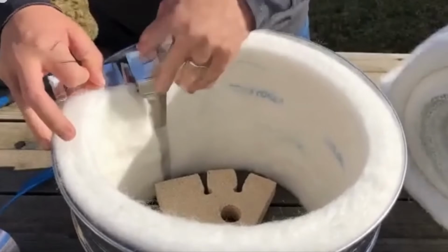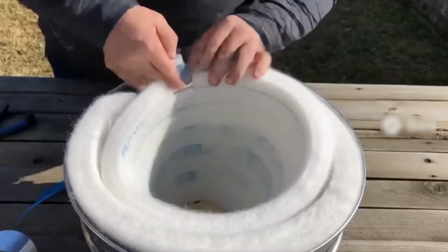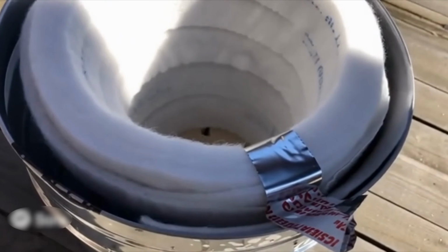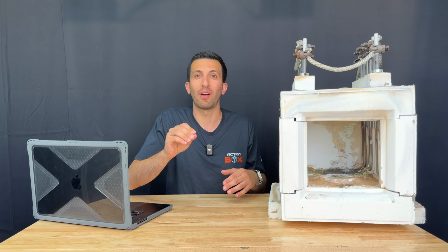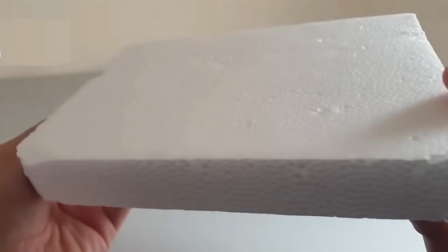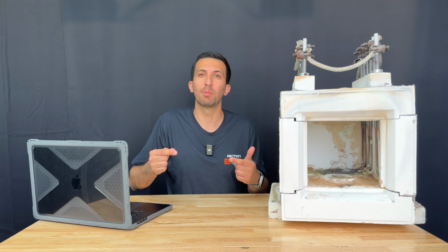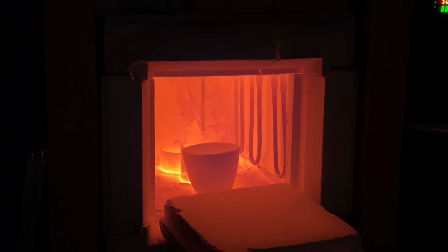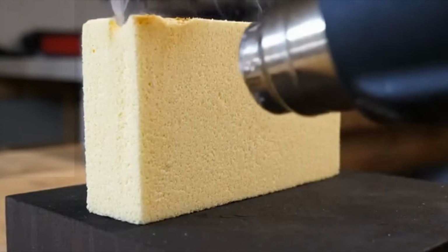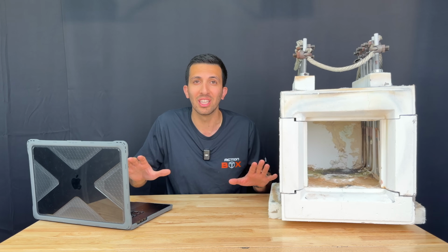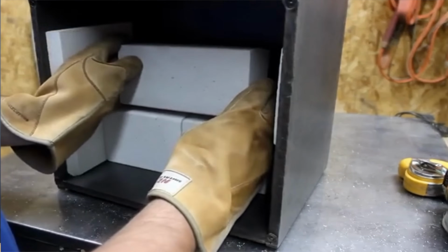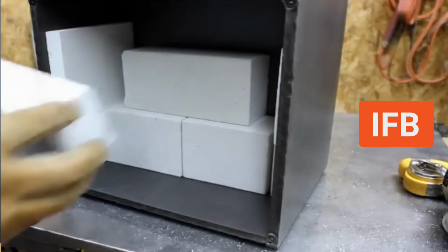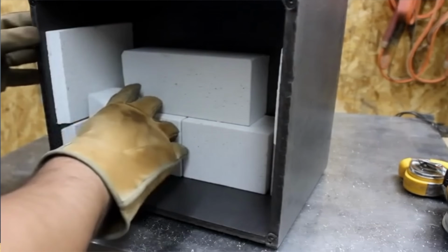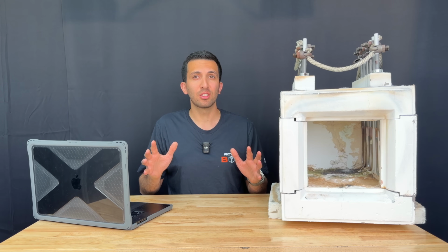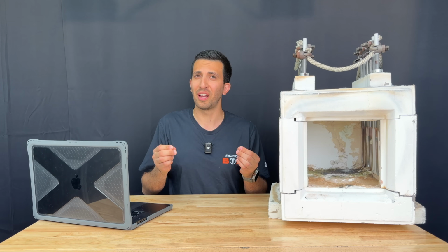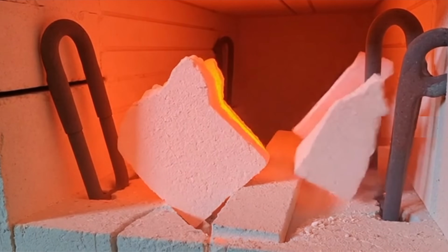Insulation is perhaps the most obvious thing to consider when building a furnace because you want to trap the heat inside. The problem is that not only do we need to find a good insulator, like this foam for example used to insulate our homes, we also need the material to survive the high temperatures. Again, this styrofoam is a great insulator, but at 600 degrees Fahrenheit, it totally disintegrates. Insulation in the common furnace is made of IFB, a material rated to 2600 Fahrenheit. But if we use that in our experiment furnace trying to go to 3200 degrees Fahrenheit, we're going to melt it and have a catastrophic failure.